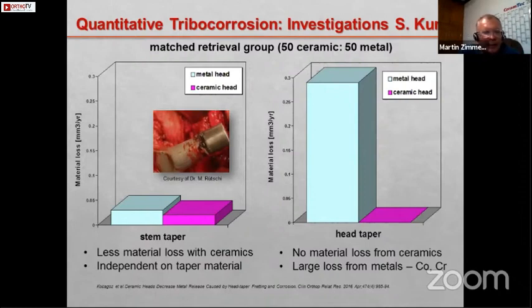and this is exactly all the problematic that you observe with metal on metal. If you look on the left-hand side with the loss of the material from the taper of the stem, we see with the pink version a slightly bit less loss of the material compared to the cobalt chrome. If you look now, again, based on the taper of the head, on the pink side, there is absolutely no loss of material coming from the ceramic ball heads.